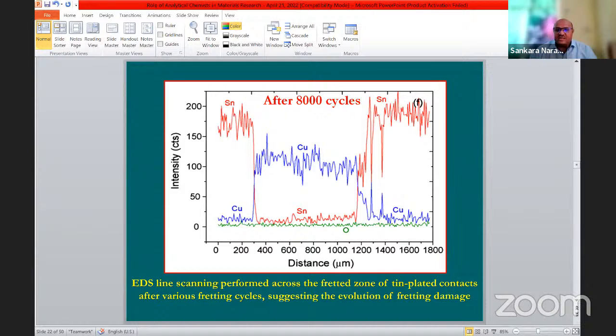After 1,000 cycles and 8,000 cycles, what happens is, after 8,000 cycles, the tin is completely removed in this area, and copper is coming up very nicely. So using the EDS line scanning pattern, the EDAX pattern, as well as the X-ray elemental mapping and scanning electron microscope, all put together, you are able to see and understand the mechanism of corrosion, how the metal is removed and it is getting oxidized.